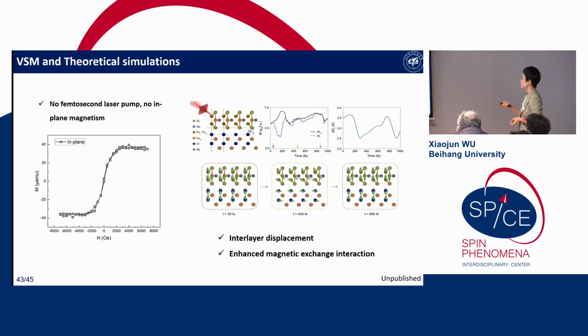To further verify that, we also did the VSM measurement, and there is no in-plane magnetization if we don't have femtosecond laser pulses illuminated on it. We found some theoretical collaborators from IOP CAS, and they gave us some theoretical exploration, saying that when the femtosecond laser is illuminated on the superlattice, it has the chance to shorten the atomic distance between them by 0.1 nanometer. Because of this shorter distance, the exchange bias effect is enhanced. Only that pushes the Curie temperature from around 200 Kelvin to room temperature.